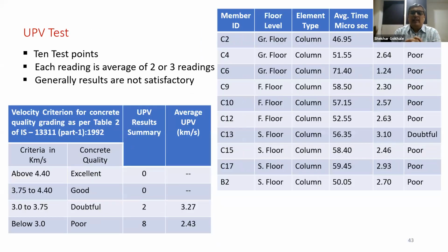Then we carried out 10 points of UPV test. These are again, out of those 18 columns, we have taken a few columns and 1 beam. Here we observed the difference. Most of the readings are doubtful and poor. So if we summarize the result, for velocity between 3 to 3.75, 2 readings are in this range, where the average UPV is 3.27, and below 3 there are 8 readings giving an average UPV of 2.43 km per second. So all the readings are of either doubtful quality or poor quality.